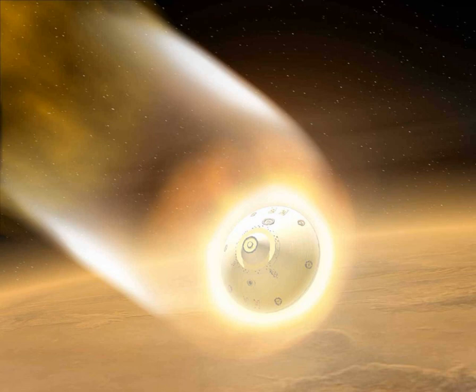SIRCA was also the primary TPS material for the unsuccessful Deep Space 2 (DS-2) Mars impactor probes with their 0.35 meters base diameter aeroshells. SIRCA is a monolithic, insulating material that can provide thermal protection through ablation. It is the only TPS material that can be machined to custom shapes and then applied directly to the spacecraft. There is no post-processing, heat treating, or additional coatings required, unlike space shuttle tiles.